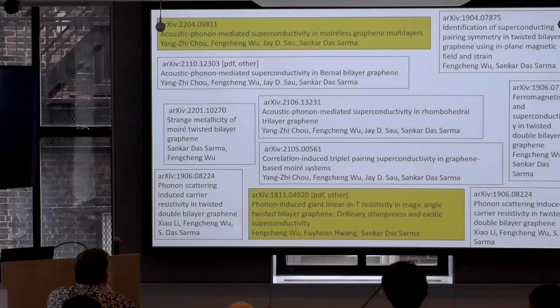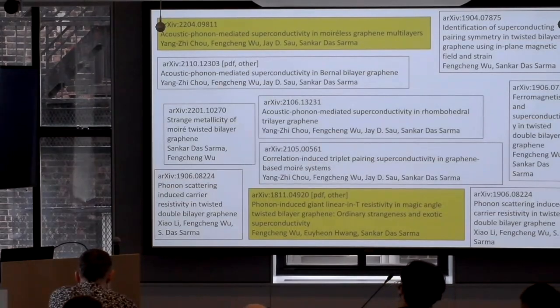We are doing the full resistivity calculation in all these systems with the full band structure. Okay, it's kind of the DMFT calculations you guys do, but for electron phonon interaction. Complete calculation. My real goal is to see whether we can push the low T linear coming from phonons all the way down to like 50 millikelvin. It goes down, but I don't think it goes down to 50 millikelvin. And this paper apparently is almost ready, and we should be posting it soon.